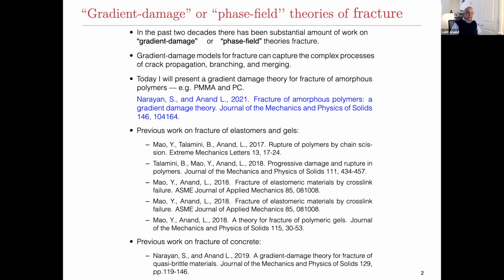But in essence, it is a damage theory, and the damage in the simplest form is a scalar variable, but you also account for the gradient of damage in a diffuse sense. There have been a number of different theories in the literature which fall under the category of gradient damage or phase field theories, primarily for linear elastic brittle fracture. But the nice thing about these gradient damage models is they can capture the complex processes of propagation of cracks, branching of cracks, and the merging of cracks, which classical theories of fracture like K1 equal to K1C or J equal to JC just cannot do.